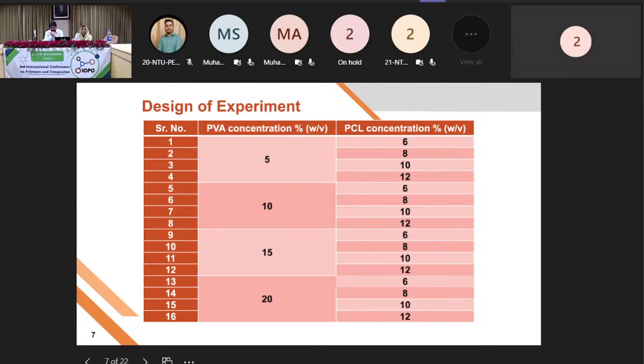We used different concentrations of the two materials in this project, polyvinyl alcohol and polycaprolactone. For polyvinyl alcohol concentrations, we used 5 to 20 weight per volume percentages. For polycaprolactone, we used 6 to 12 weight per volume percentages. All of these different ratios were developed so we could analyze the effect of different concentrations of each material. Later on, we will achieve the best possible blend ratio, which will provide the required properties for medical applications.